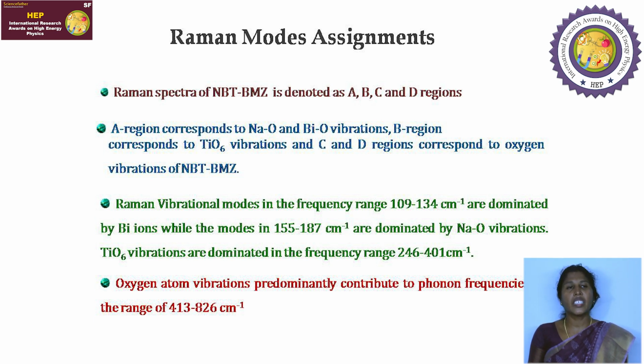Then the B region is related to TiO6 octahedral vibrations, and the C region and D region, that means beyond 400, are related to oxygen phonon frequencies, that means oxygen vibrations. Theoretically we know that there are 13 modes. Experimentally we can observe only 10 or 11 modes. Out of these, the ETO1 mode is predicted theoretically, but it is not observed experimentally.